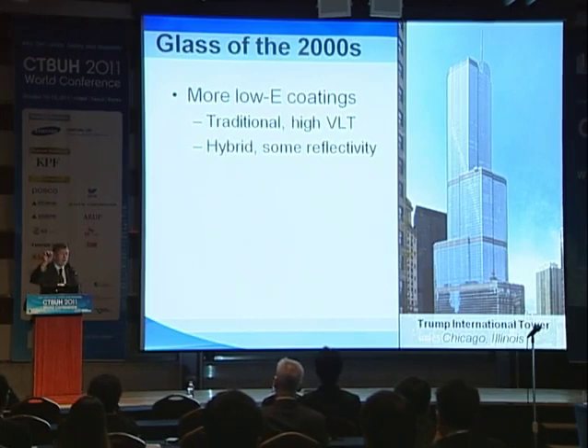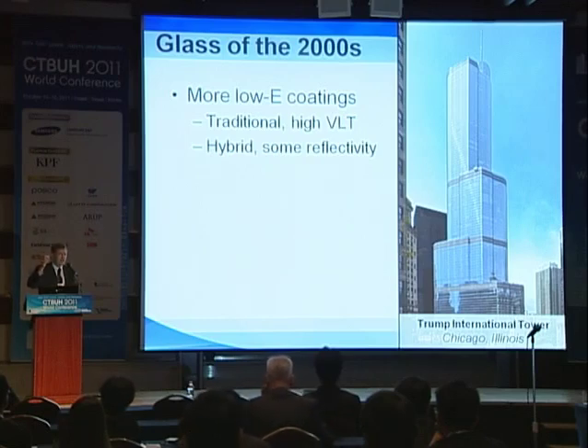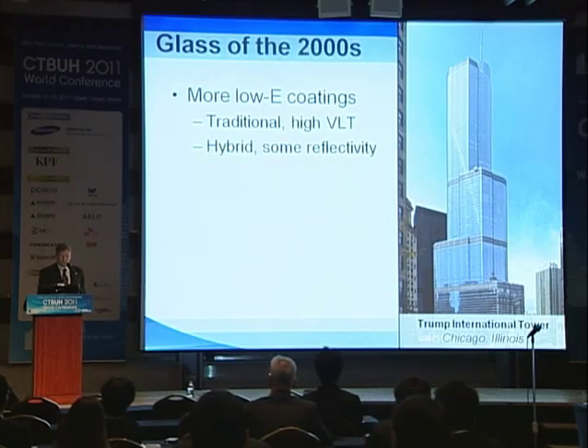Also, when we were talking about high-performance reflective coatings, those shiny buildings, they did not have very good U or K values. The low emissivity coatings have excellent U values, K values, and that comes from the improvement of the silver products that are on those particular coatings. So these hybrid coatings gave you the benefit of improved high performance, shading coefficient, solar heat gain coefficient, gave you the ability to have some light transmission, excellent K values, U values, but also, as you can see, gave you the ability to have some degree of reflectivity.